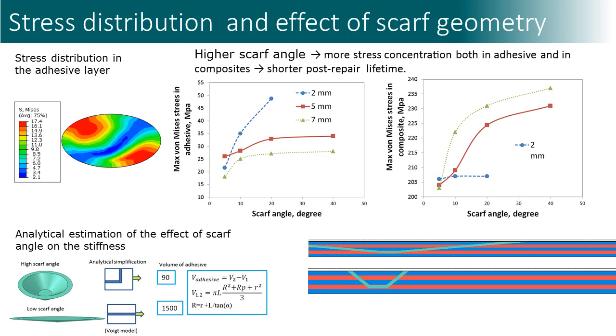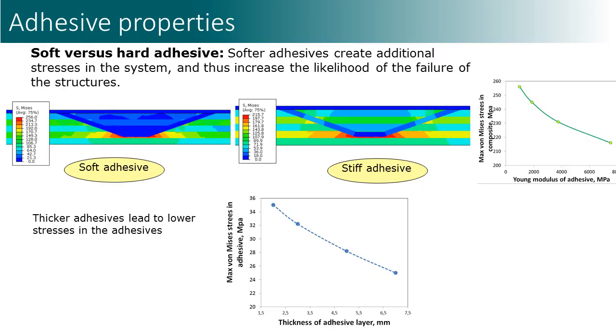A number of computational studies were carried out. One observation is that the most dangerous area in the adhesive is close to the upper part, the coating. Further, we studied the effect of the adhesive thickness and scarf angle. It was observed that a higher scarf angle leads to higher stress concentration both in the adhesive and in the repaired composite. The model was validated by comparison with a simplified analytical, Voigt-type model. The computational studies also demonstrated that soft adhesives create additional stresses in the system, as compared to stiff adhesives.